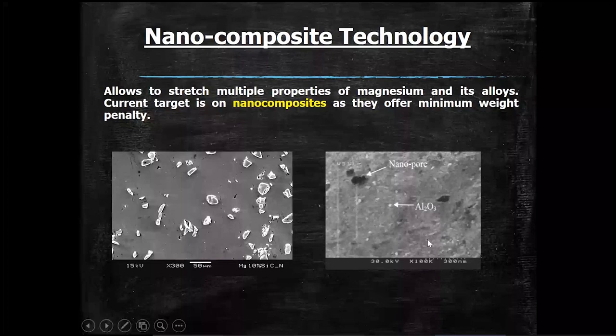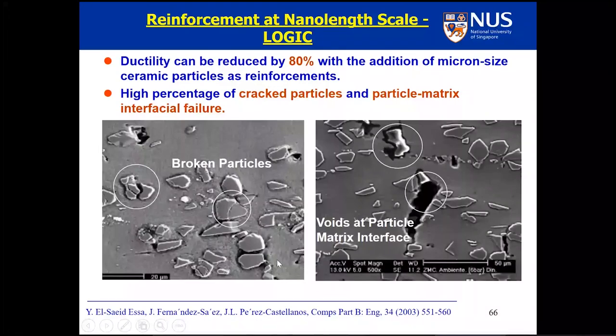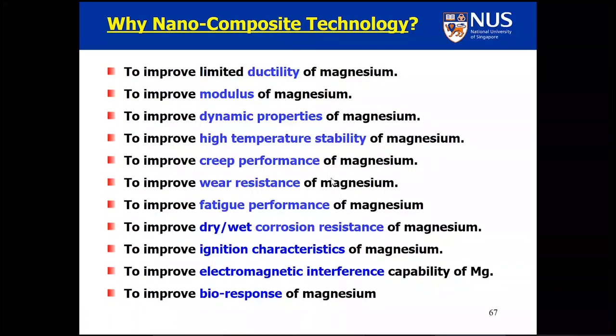The problem with the big, micron-sized particles is that when you apply the tensile load, these particles break or debond. Once they break or debond, stresses act on that and your material fails prematurely. Your ductility is compromised by 80% and your toughness is equivalently compromised. So you are not able to realize good properties of your material. Using nano reinforcement is very important because in the case of magnesium, it helps in improving the ductility, modulus, dynamic properties, high temperature stability, creep properties, wear properties, fatigue, dry and wet corrosion resistance, ignition, electromagnetic interference, and the bioresponse.